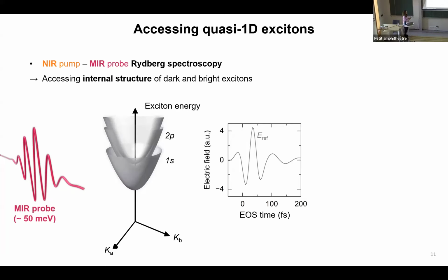So how can I make my system react? I have to generate the excitons because they do not exist initially in the material. So we pump the excitons to the conduction band or somewhere above the excitonic bands. They relax to the 1s state, and then they start to scatter across momentum space because of different scattering phenomena. So these excitons can no longer recombine to the ground state by simply emitting a photon. They go dark and we lose information about these species.